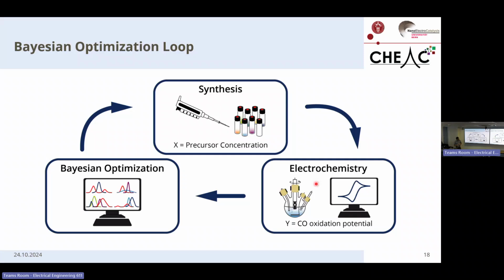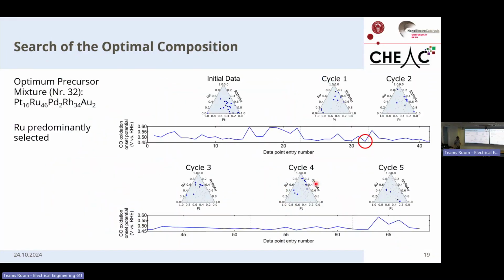Right now, as I am trying to optimize something that I can control, I decided to optimize the precursor ratios in the synthesis process. Because the precursor ratios I can control, whereas the composition that I'm getting out of it is a consequence of the synthesis. So strictly speaking, I was optimizing the synthesis to produce the most active catalyst. The results are then shown over here.